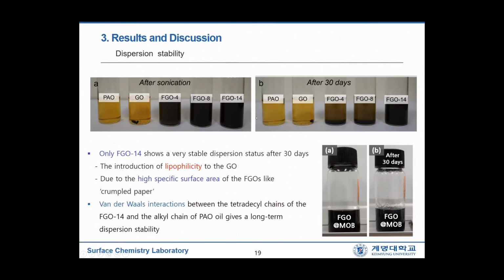This is also due to the high specific surface area of FGOs, like crumpled paper. It revealed that van der Waals interaction between the tetradecyl chains of the FGO14 and the alkyl chain of PAO oil gives a long-term dispersion stability.